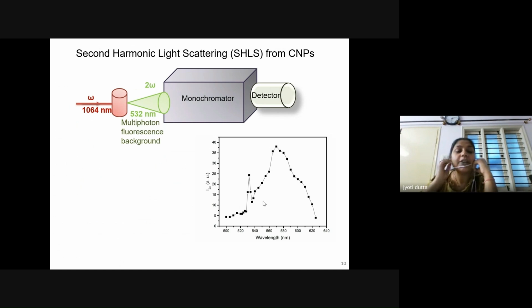Now this is checked for all the materials for which we check the nonlinear property, whether these molecules are also associated with any multiphoton fluorescence background. So in case of carbonaceous nanoparticles, we observed that the second harmonic peak, which is at 532 nanometer, is riding over a broad multiphoton fluorescence background which is peaking at 570 nanometer.